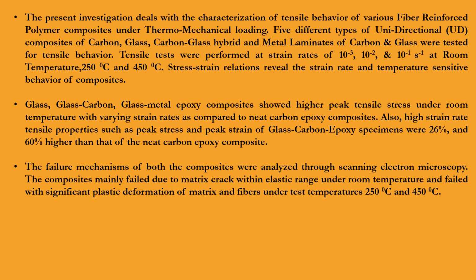Glass, glass carbon, glass metal epoxy composites showed higher peak tensile stress under room temperature with varying strain rates as compared to neat carbon epoxy composites. Also, high strain rate tensile properties such as peak stress and peak strain of glass carbon epoxy specimens were 26% and 60% higher than that of neat carbon epoxy composite.